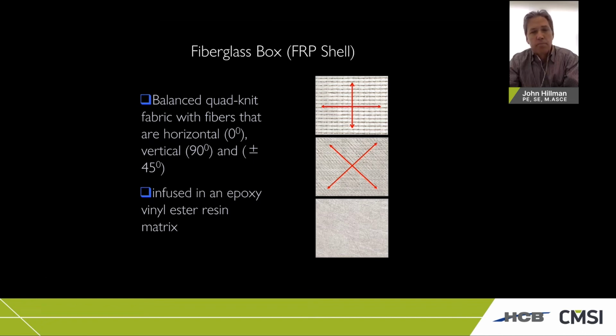Just a brief overview of this particular type of composite. We use what's called a balanced quad knit fabric. That means you've got a fabric that's got multiple layers of unidirectional glass in 4 different directions. So we've got longitudinal, transverse, and then plus minus 45 that gives us our shear capacity, and then usually just a continuous strand mat that gives us some stability. It's infused in an epoxy vinyl ester resin, or epoxy or polyester resins, and what results is really a fiber reinforced polymer material that gives us quasi-isotropic behavior. So we're basically getting the same material properties in every different direction with the balanced fabrics.